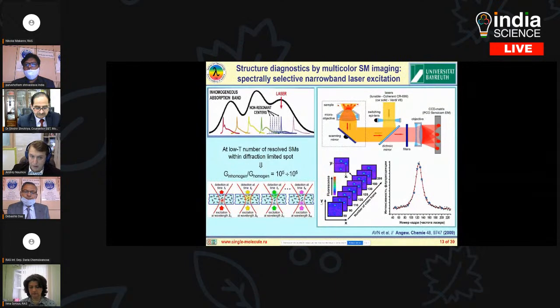But what is very important, we can do not only single molecule spectroscopy, not only spectroscopy for one molecule, but also for many molecules. But now we don't need to realize blinking of our labels, because you see we have a strong distribution of this spectrum along the spectral range. So if we have a tunable narrowband laser, for example a dye laser, and we tune the laser excitation wavelength, we can excite different molecules separately in different diffraction limited volumes. And we automatically solve the problem of recognition of a lot of label molecules.